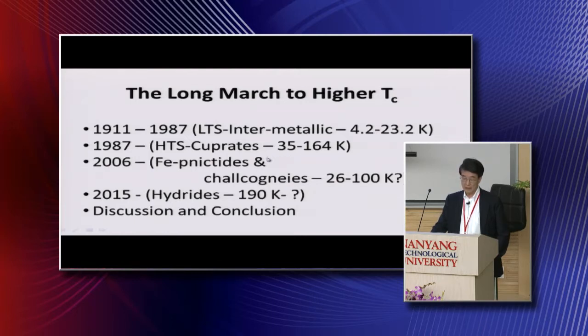And then later on, in the year 2006, a new class of material was discovered by Hosono and coworkers, and it basically concentrated on iron pnictides and chalcogenides, and the transition temperature goes from 26 to 100 degrees Kelvin. And then, of course, what happened recently is the announcement by the Germans on hydrides, with the transition temperature up to 190 degrees Kelvin, but under extremely high pressure. And then I'll conclude my talk.